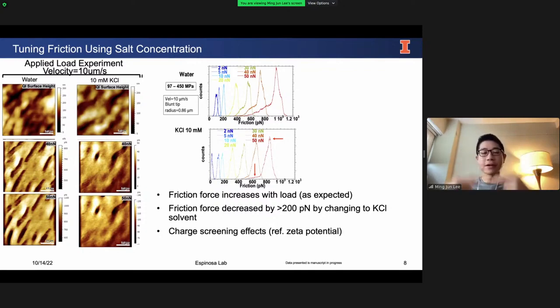And this ties back to the charge screening effects that I mentioned in the previous slide, because the surface of these hydrogels have acrylic acid groups, so carboxylic acid, that's COO minus, negative terminated. But then the AFM tip is made of silicon, and it's terminated with the silanol groups, the SiO minus groups. So having both negative charges in the AFM tip as well as hydrogel surface leads to repulsion between these measurement devices, and that lowers the friction force that's being measured by the AFM.